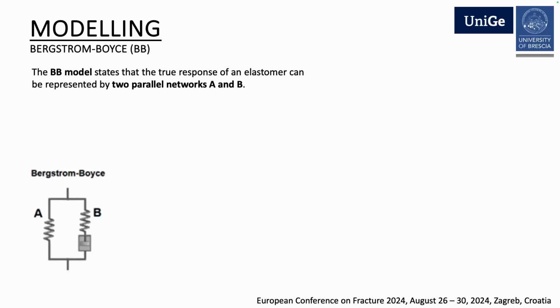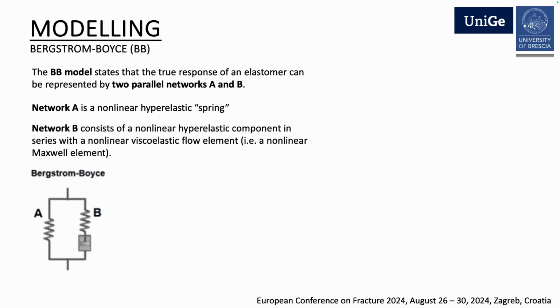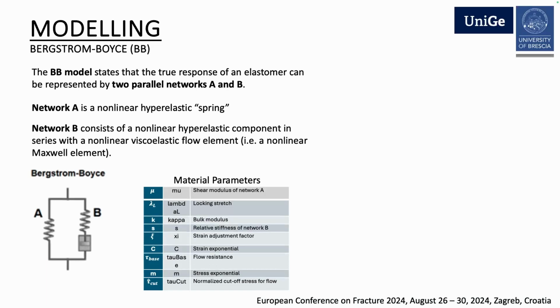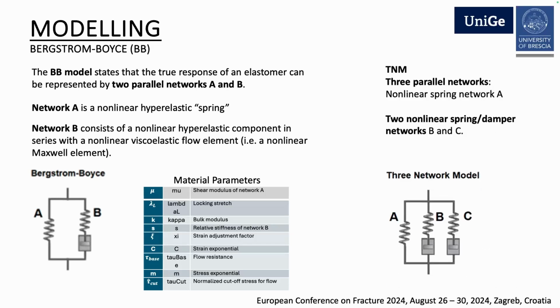So here you can see the Bergstrom-Boyce model, which is well established in the literature. It consists basically of two networks. The first network is a nonlinear hyperelastic spring, and the second network is a sort of nonlinear Maxwell element in which we have a further hyperelastic spring in series with a nonlinear viscous element. So this model requires for its calibration 9 material parameters. And another model that we have considered is the so-called three network model. In this case, the main difference is you have an additional nonlinear Maxwell element. So that means that potentially you have improved your predictive capabilities, but at the price of more material parameters to be determined.